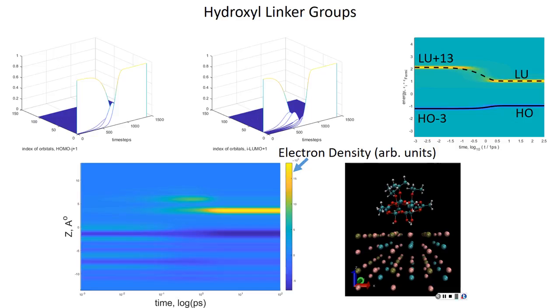The hole is kind of... So you just put a hole there, at this energy, and then the hole will move to your metallic contact with the right electronic levels, wherever would be right for this energy level. It may return back and recombine on the perovskite if you do not add specific layers that will pull the hole out of the perovskite. Before you add metal contacts, you need two additional layers.